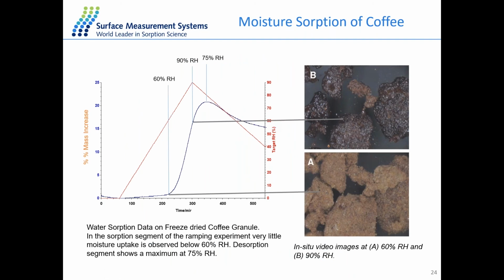Another ramping experiment we performed was with coffee granules, where we exposed the sample to humidity ramping first from 0 to 90% RH and then decreasing to 40% RH. And we also took some photo images during the sorption and desorption steps. So during the sorption process, you can see up to 60% RH there is not much difference in moisture uptake. But after that, there is a sharp increase. At 90% RH, the in situ image also shows the sample has already changed color compared to 60% RH.